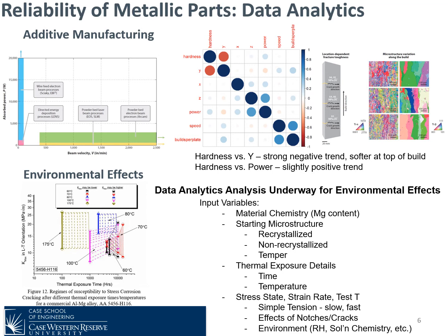In the additive manufacturing community, as I alluded to before, if you look at the power velocity regimes of any additive process, there is a wide range of powers and velocities, even within the green region here. And so one of the students that has taken Professor French's class has taken her data, which was done on a stainless steel, and looked at, what's affecting the properties. And this first cut was looking at power and speed. How does it affect the hardness, which would correlate with the strength? How is that affected by X, Y, and Z in the build, and how many builds per plate?